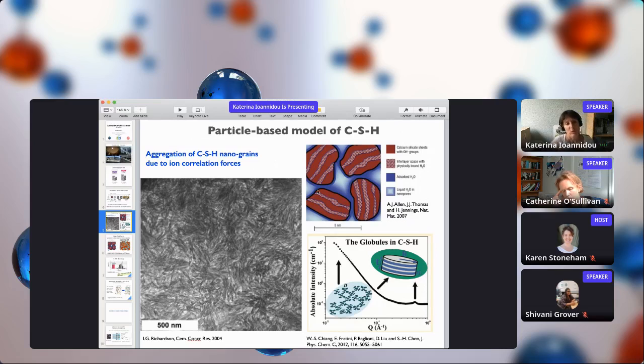This model is based on particles. There are indications from scattering experiments that we have a particle-based material around the size of a few nanometers. There are also models proposed in the past by Jennings, suggesting particles of 5 nanometers that have a complex inner structure, and these particles are agglomerated together. We can see from an SEM picture that this material has some local structure, but overall is very amorphous. So the goal of this modeling study is to start from particles of a few nanometers, figure out the interaction between them, and produce an amorphous structure with stabilized porosity that is realistic for a material like cement.